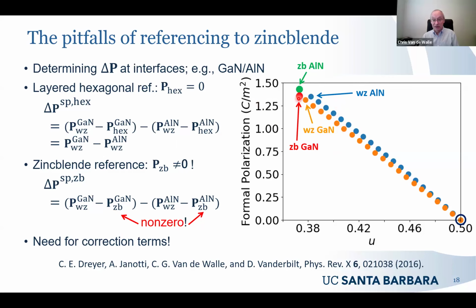So these terms that enter because of our choice of reference structure are non-zero, and they would need to be taken into account anytime you do a calculation of a polarization discontinuity if you choose the zinc blende as the reference. Okay. And the sad thing is that this has not been done. And as far as I know, even in the device simulation tools that we are using to date, this is still not correctly implemented.